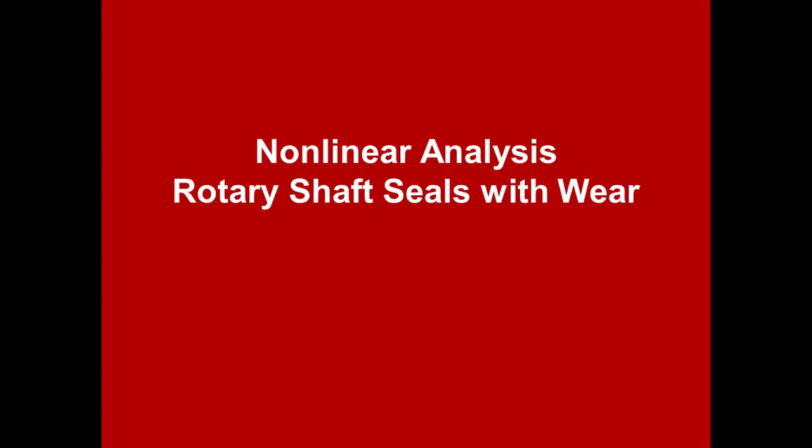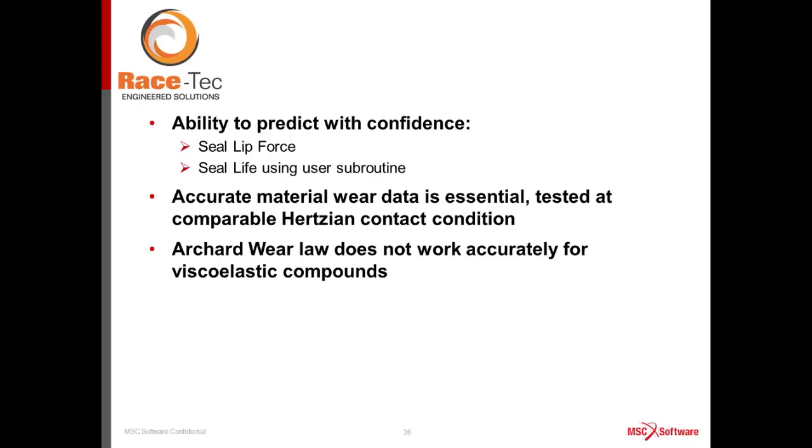One final application area that I was going to share with you was the analysis of rotary shaft seals with wear. We use a user subroutine which allows us to predict the level of force and therefore the level of wear that occurs on a seal during operation. It allows us to predict using the software the exact lip force, and then using the lip force and the user subroutine we can actually predict with a degree of confidence the life that the seal is going to attain.